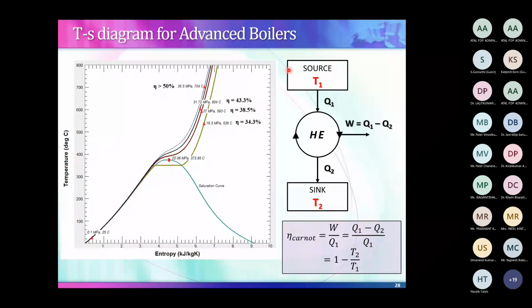So this is my subcritical line, 22.06, and we are getting 34.3%. Then this is my supercritical, 27 megapascal, 593, 38.5. And then this is my ultra supercritical, 31.72, 604, and 43.3%. And this is the latest, 36.5, 704 degrees centigrade, so greater than 50%. That means now we have to switch from subcritical to supercritical or ultra supercritical to achieve higher efficiency from the boiler.